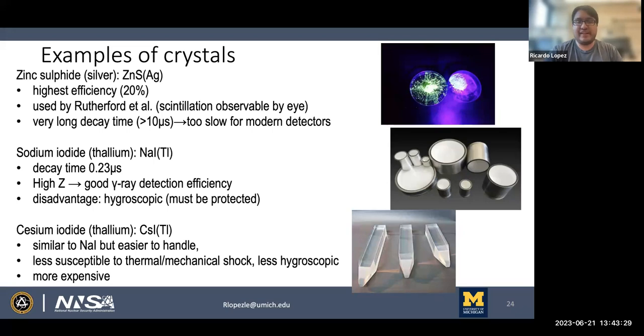However, the resulting recoil electrons that you get from Compton scattering within the crystal could just end up making their way through the crystal and leaving the volume before they're able to deposit most of their energy. So often, a very large inorganic scintillator is desired, since you're able to get the majority of your energy deposited from your events in that case.